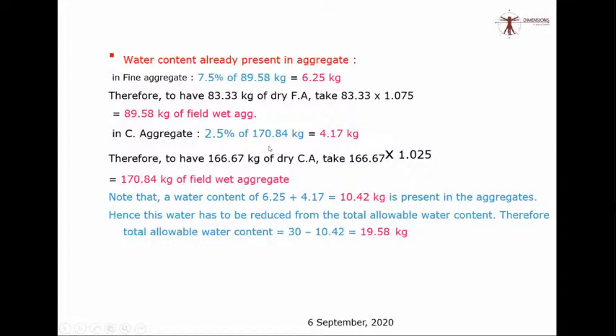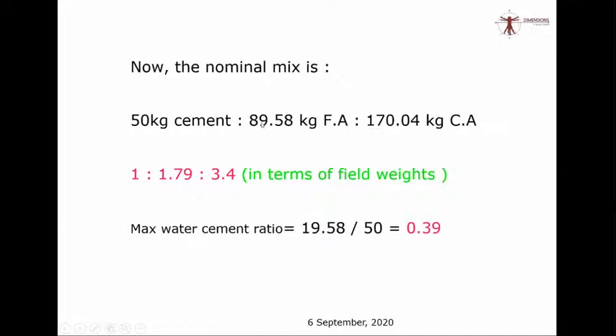And similarly for coarse aggregate, you will do the same exercise. Initially you got 166.67, you will have to multiply 166.67 by 1.025. So you will land up in 170.84 kg. Now your new ratio would be 50 kg of cement. Instead of 83.33, you will multiply it by 1.075. So your weight of fine aggregate is 89.58, and your weight of coarse aggregate is 170.04.